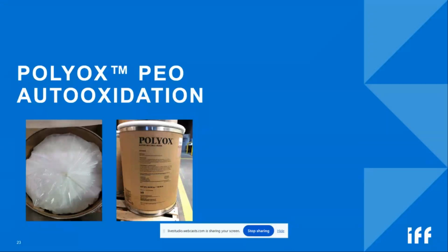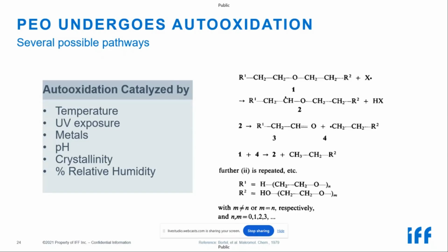Now I want to move on to auto-oxidation of PEO. PEO undergoes auto-oxidation. There are several pathways it can go through. I'm just showing one potential pathway using a free radical, where you're essentially causing chain scission of the chains. That chain scission reduces the molecular weight, which reduces the effective observed solution viscosity of the material.